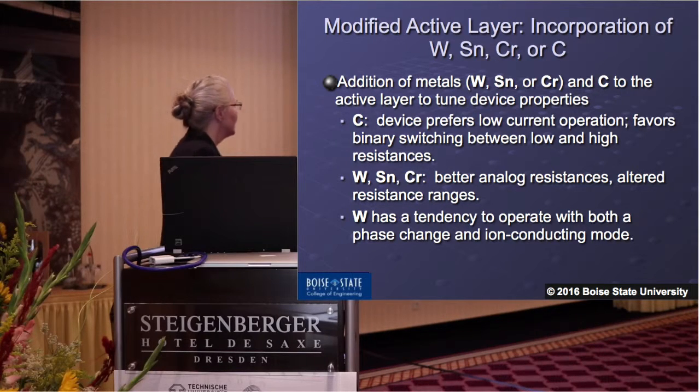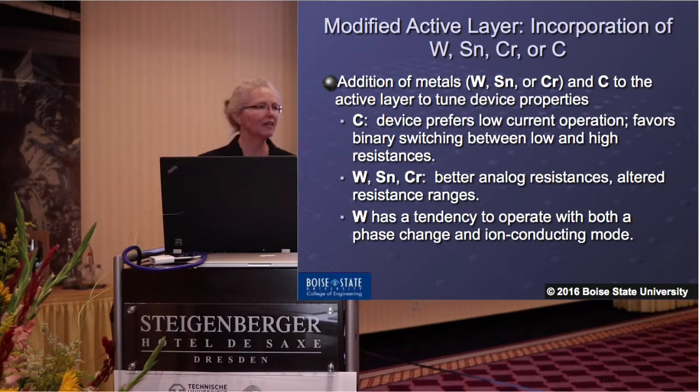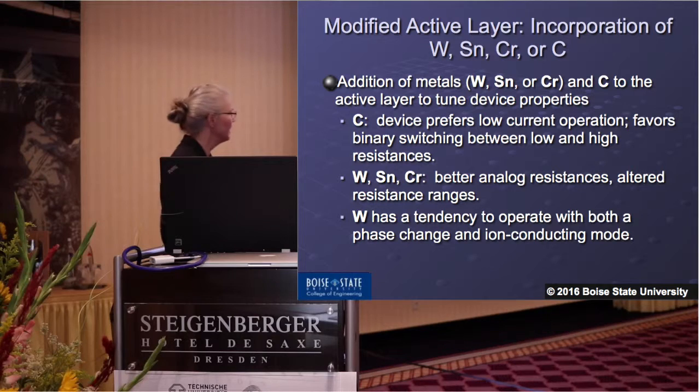What they did was they switched. They liked very low current. They were clean switching devices. And by low current, you want a compliance current of 100 nanoamps on those. Otherwise, it tends to cause the device to get into a low resistance state and not want to leave. And the operation, it was hard to find anything when switching with a quasi-static system, hard to find anything that wasn't binary. I'm sure it's there. We didn't pulse it very well to see, but it was an interesting system.